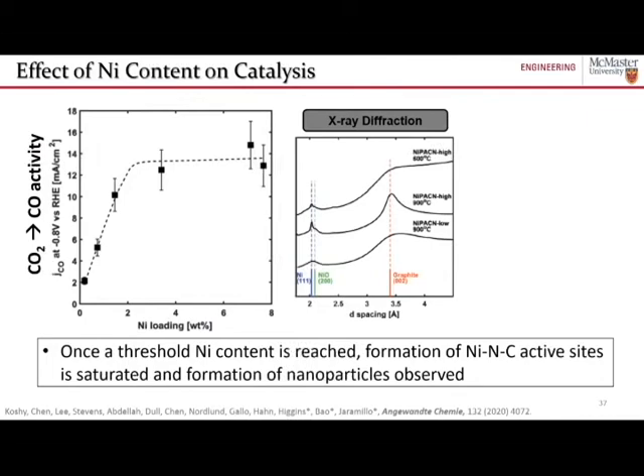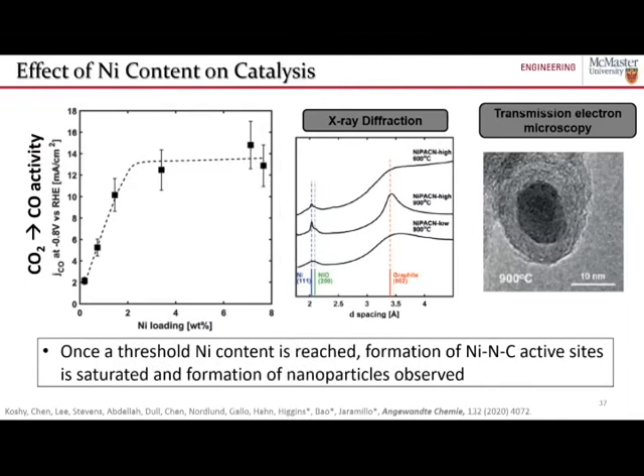Now, one thing that surprised us about that is that if we knew we had nickel metal or nickel oxide nanoparticles in these materials, it's well known that nickel on its own in metallic or oxide form is going to be reduced under electrochemical conditions, and that nickel can be very selective for the hydrogen evolution reaction. So we asked, why are we still seeing high selectivity for carbon monoxide even when we have these nickel nanoparticles in the materials? The reason being is when we did some high resolution TEM on these materials, the nickel nanoparticles had a graphitic shell around them that protected them and prevented any reactants from accessing the nickel, thereby blocking them as hydrogen producing components of this catalyst and allowing us to maintain our high selectivity towards carbon monoxide.